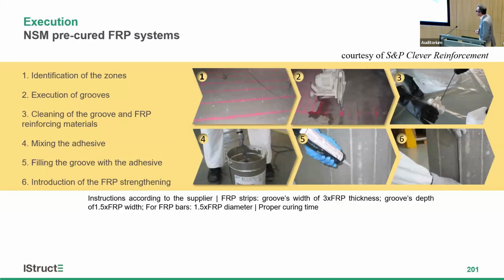Finally, in the case of near-surface pre-cured systems, the first step is to identify the zones where we are going to apply the composite material. Then open the grooves, typically using saw machines. Here it helps because gravity is helping. When we have to do it, for instance, for positive bending moments, it's more challenging, but it is feasible. Then we also have to cut and clean the composites, prepare again the adhesive, apply the adhesive inside the grooves, and then we install the CFRP system.